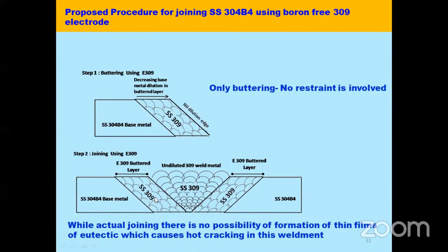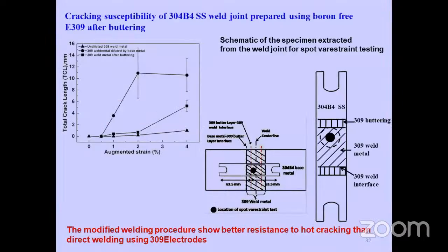So next we are going to use the same E309 electrode to join the buttered surface. While joining, you have the restraint arising from the geometry and solidification. But here the interdendritic liquid, that is the boride low melting eutectic coming from the base metal dilution, is not present. So here we have restraint but no liquid material surrounding the interdendritic boundaries. In this case, we are able to curtail the hot cracking that forms during welding of this borated stainless steel. So this we have demonstrated.